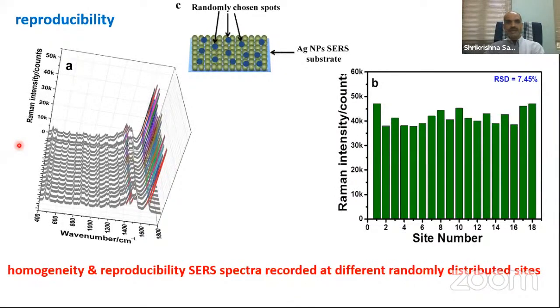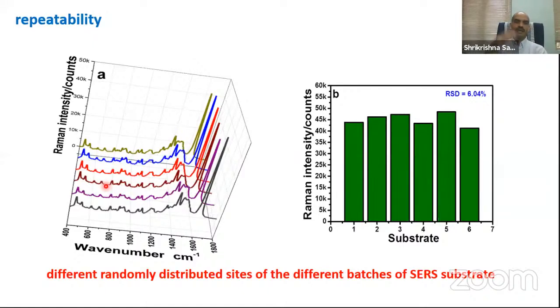Not only that, you have to have repeatability. What does it mean? If I make one substrate, then another, a third, a fourth, and so on and so forth, do I get the same intensity? If I get the same intensity, then you can say that your process is repeatable. So repeatability is also an important factor. We can see that the SERS signal is almost the same.